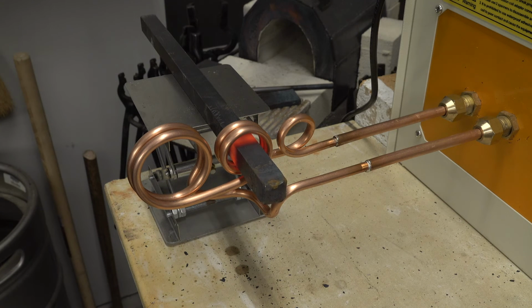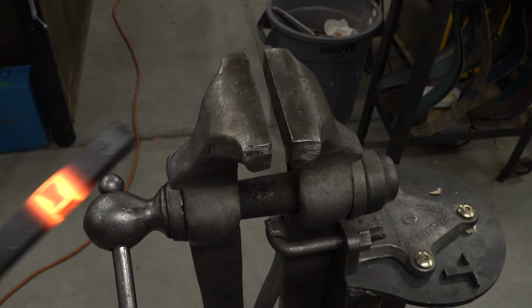As you can see, with only 2 turns in the center coil, it takes considerably longer to heat up the cross section of material. However, given another minute or 2, it can easily get up to a nice forging heat.